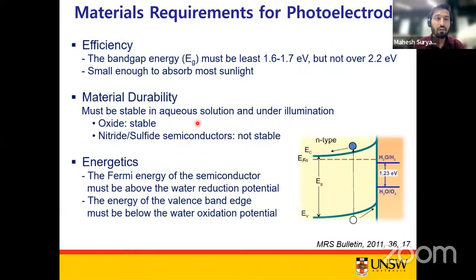We need high quality semiconductor materials that can sustain as well as perform very well in aqueous electrolytes to produce the hydrogen. So usually an ideal material that people think of as good photoelectrodes for carrying out these water splitting reactions should possess a suitable band gap to allow the light absorption and the electron excitations with a sufficient energy, usually greater than 1.23 electron volt, or equivalent to about 237 kilojoule per mole, without considering the overpotential.